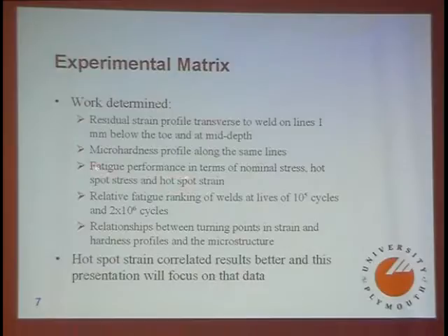So what we've then done is we've had a look at the fatigue performance, and we've only used 3 ways of doing this. Nominal stress, which I didn't expect to work very well and didn't, but hey, it's there, we do it. And we had a look at hotspot strain and hotspot stress, in other words, the structural stresses at the weld toe. And it turns out here that the actual hotspot strain, which is what you might expect, does a better job of correlations, but you don't a priori know that, so it's worth having a look.